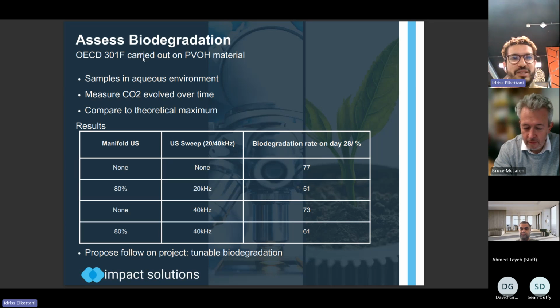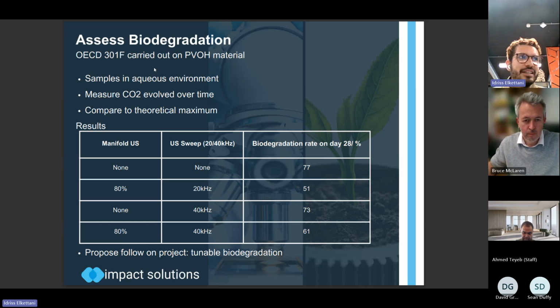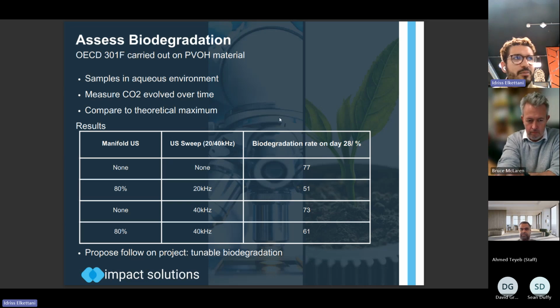But essentially, we grind up the molded component into a powder, and we put a known quantity of that powder in a flask that contains activated sludge, and we connect that to a respirometer that can measure the CO2 over time. And using some equations which link up the CO2 production and the composition of the polymer, we're able to then work out the biodegradation rate on day 28. So for a polymer or a prototype to pass the OECD 301F, it needs to show that it has degraded above 60%. So the results are quite interesting.